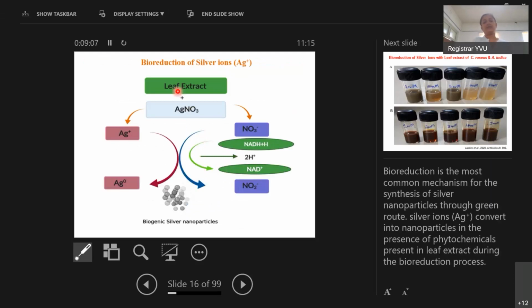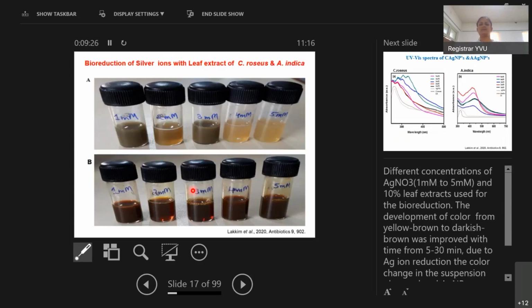This silver nitrate reduces the phytochemicals present in the leaf extracts of Catharanthus roseus and Azadirachta indica through a bioreduction mechanism. The dehydrogenation reaction reduces silver ions, forming the green synthesized silver nanoparticles. This is the colorimetric method. Bioreduction is shown with 1 millimolar to 5 millimolar silver nitrate at different concentrations.